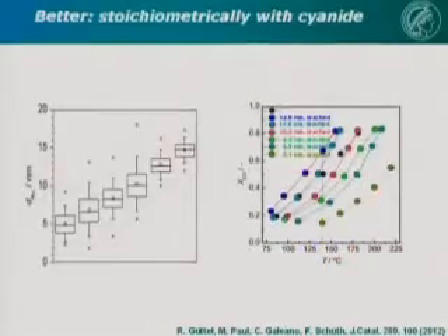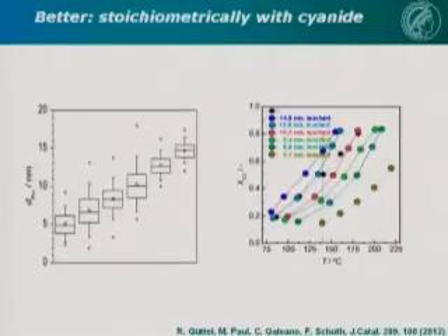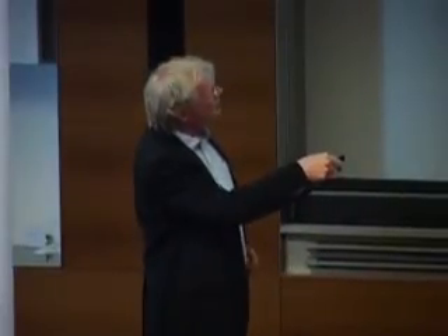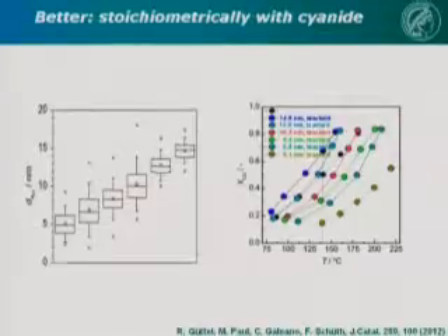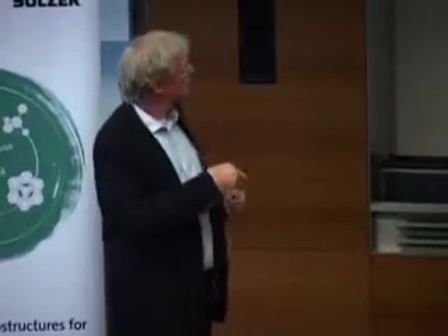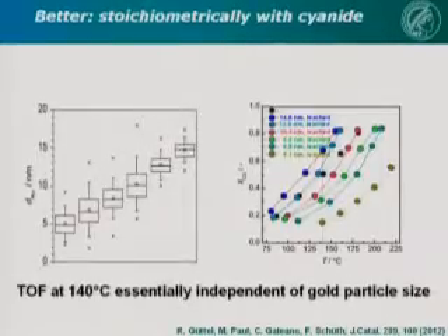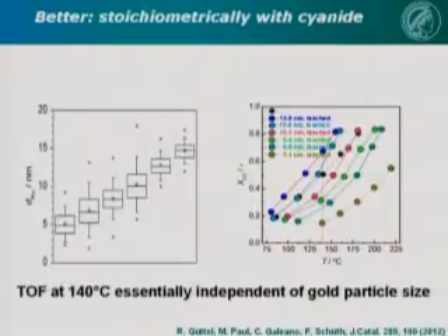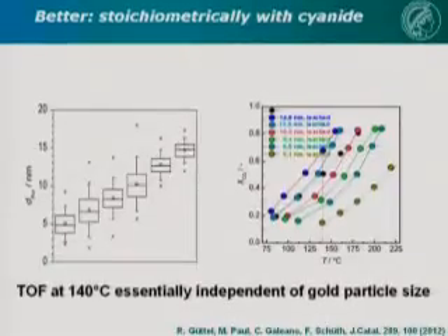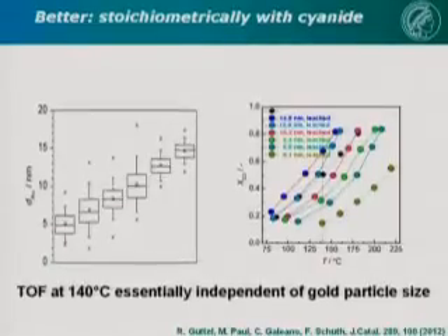Then we did a series of leachings. The size distribution for the smaller particles gets wider here. But what we basically see is all the catalysts are active. We have different activities here, but you have to normalize to surface area to get real information on the intrinsic activity. And the bottom line of this analysis is, for these particles sized above 5 nanometers, turnover frequency, catalytic intrinsic activity is essentially independent of the particle size of the gold. So the high activity really only sets in at smaller particle sizes below 5 nanometers.